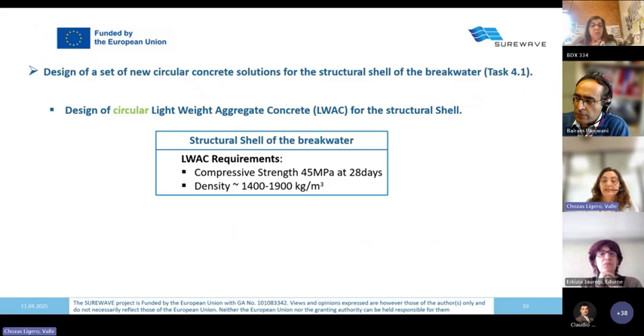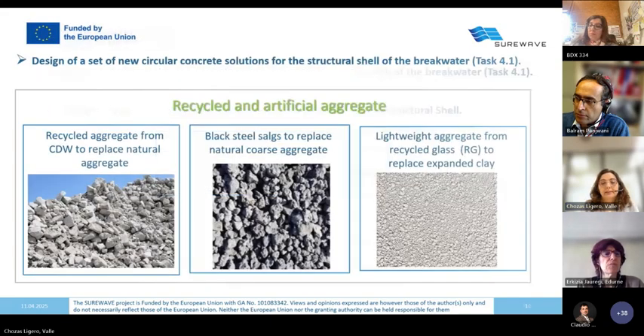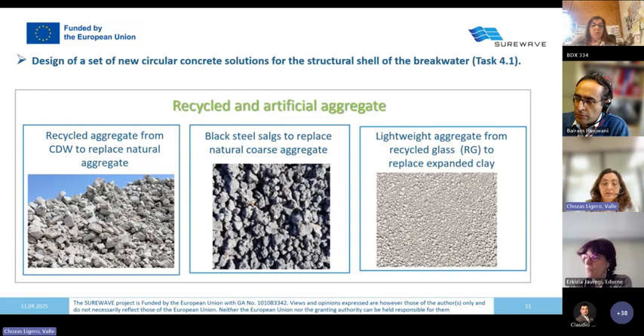In this case, the set requirements were 45 megapascal of compressive strength at 28 days, and a density from 1,400 to 1,900 kilograms per cubic meter. The target was to replace natural aggregates with recycled or artificial aggregates. For example, we recycle aggregates from construction demolition waste, also black steel slag, and lightweight aggregate from recycled glass, in this case to replace conventional expanded clay.